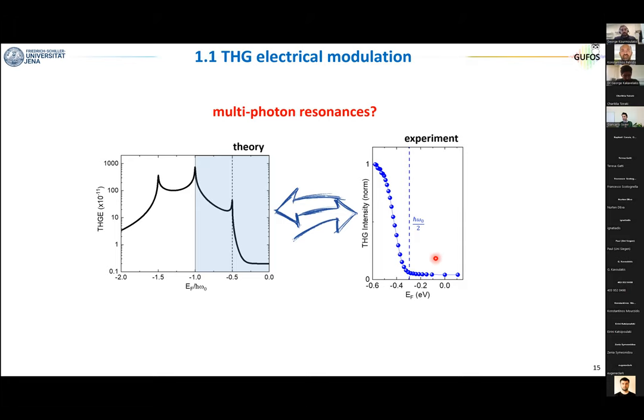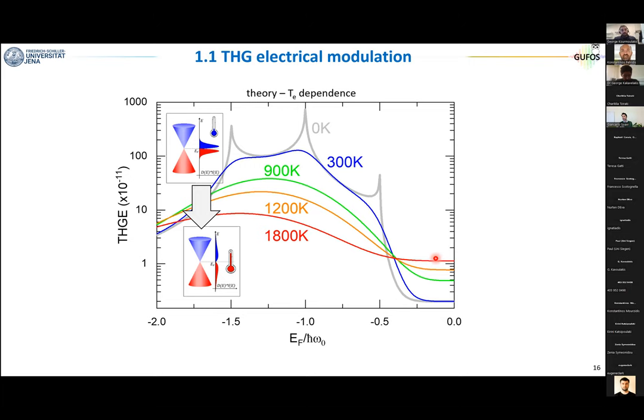So now you should argue either our experiments are wrong or our interpretation is wrong or something is missing. And let me tell you that the answer is that something is missing, because until now I was a bit cheating. The theory that I showed you works only when the electronic temperature is equal to 0 Kelvin. Now 0 Kelvin is something that does not exist in experiments.